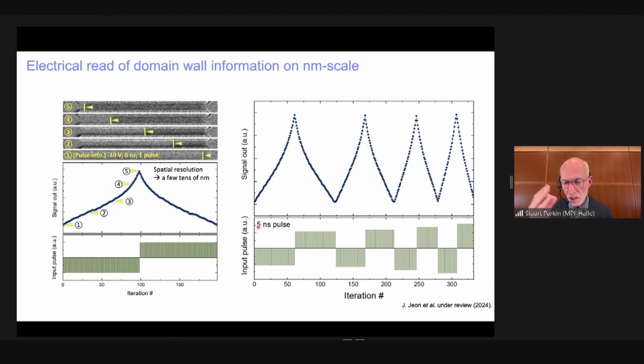And this means that a single domain wall, we can follow its trajectory and prove that it moves without any hindrance all the way along these extremely nanoscopic wires. And at the bottom, you can see the types of current pulses we're using are increasing in intensity from the left to the right as we increase the iteration number. And this is why the domain walls will go faster when the intensity of the current pulse is increased, shown here.